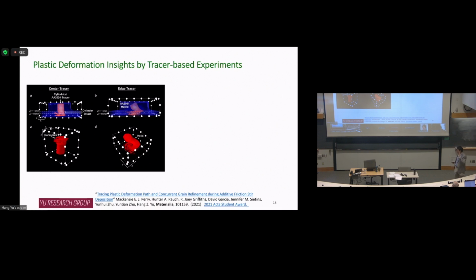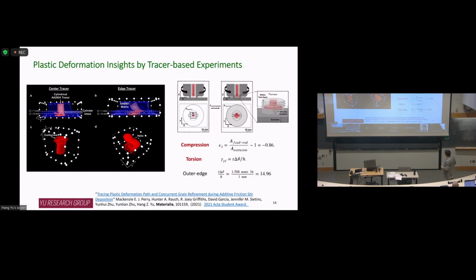But anyway, we have done some detailed examination of the shape change, and we can estimate the strain inside. I have to say the plastic deformation is history dependent, so you cannot just look at the initial shape and final shape and make a conclusion. You need to really go to the intermediate steps. But for the sake of understanding the order of magnitude, this is sufficient. So there are basically two sources of strain. One is compression as you feed the material. The other is torsion because there's a rotation rate gradient. The general conclusion is this is a large deformation. The cumulative strain is on the order of 10 or above.